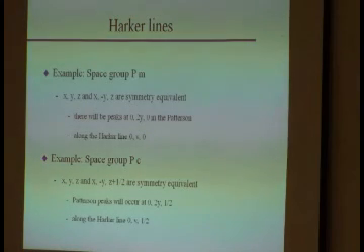Now that means for any atom at xyz, we have an equivalent atom at x, y bar, z. If I have a heavy atom at xyz, there is another equally heavy atom at x, y bar, z. And that interatomic distance between these two should show in the Patterson map, right? That is what a Patterson is all about. What is the distance between these two?